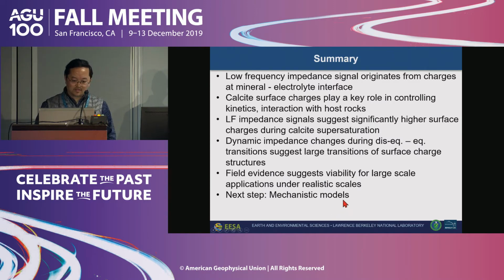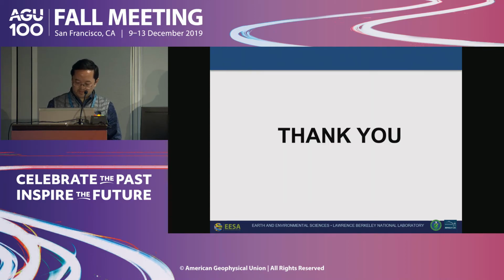Just to quickly summarize, the frequency data we're observing is linked to the interfacial property. The calcite surface charge plays a big role in controlling the kinetics of calcite precipitation in interaction with host rocks. The low frequency impedance gives us a great tool to sense interfacial charge, and how the system transitions in and out of equilibrium can result in a large impedance signal change. The data from the field suggests that this is a viable tool for large-scale applications under realistic conditions. We're working on coming up with a mechanistic model to understand how this interaction is happening. And with that, I'll stop. Thank you.